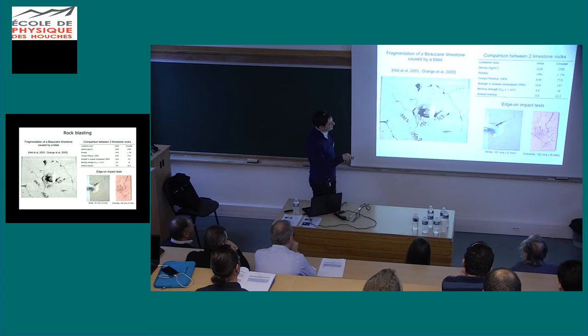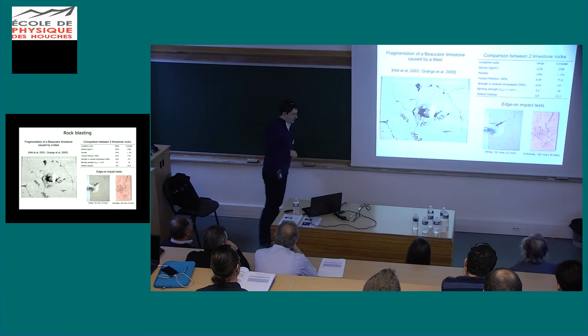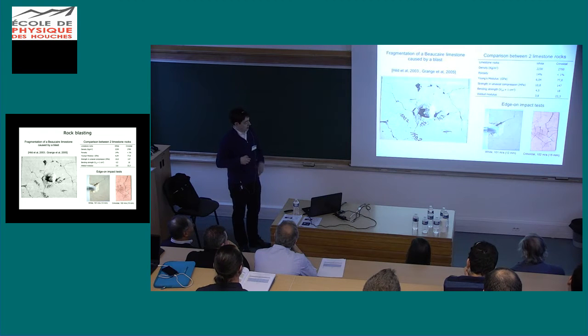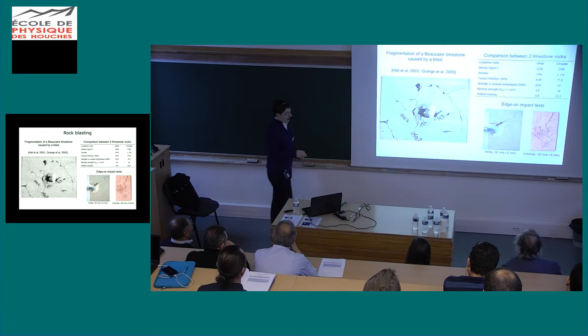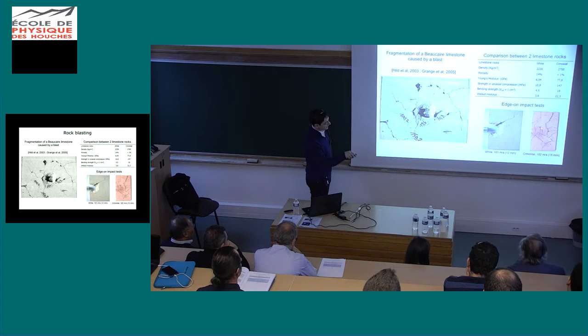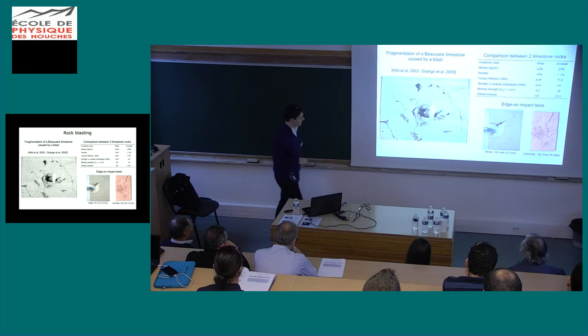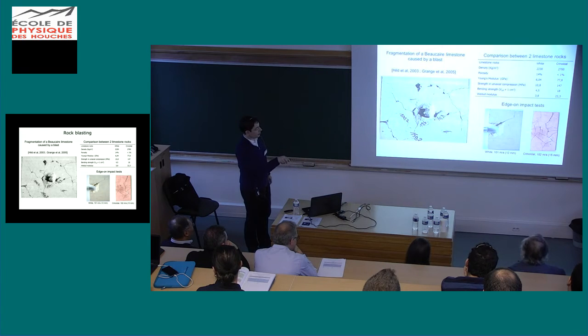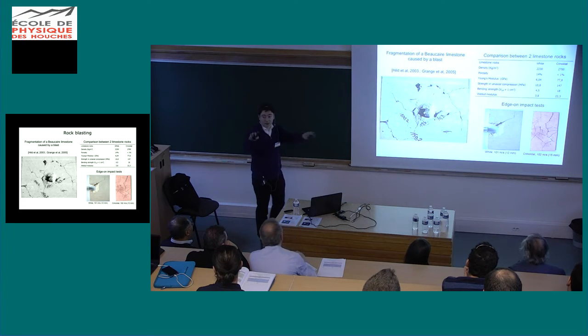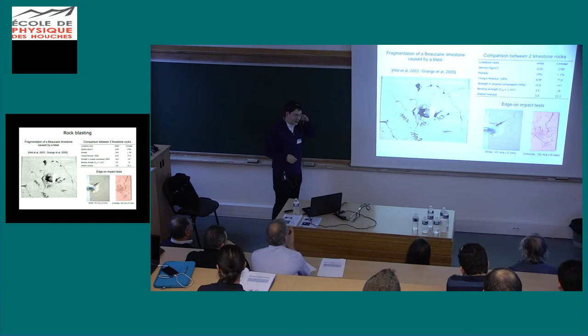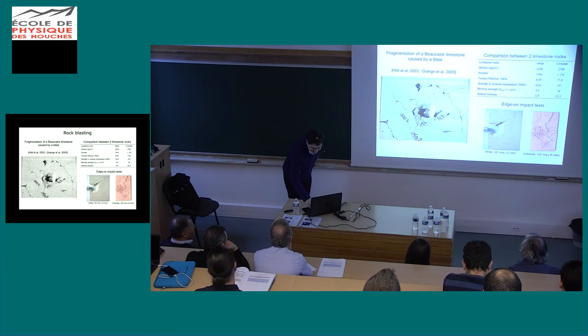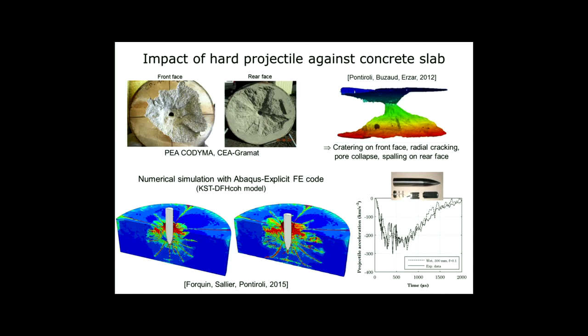And the explanation was given from these edge-on impact experiments. You can see, in fact, it was demonstrated that in the weak rock, the compression damage completely absorbs the kinetic energy. And that's why it was so difficult to generate new cracks in the rest of the volume. Whereas in the crinoidal rock, it was much easier to let the cracks propagate. Okay, I hope it's not too heavy. Okay, it's okay.